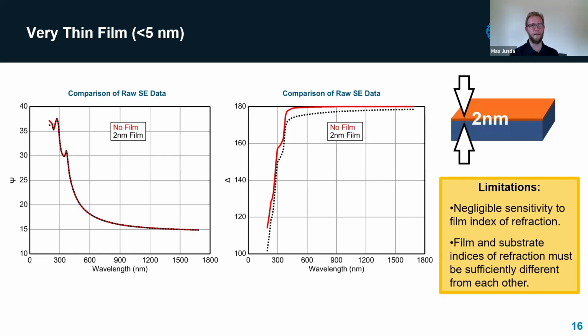And this gets to some of the limitations for very thin films. In particular, psi gives us a lot of sensitivity to what the properties of that film are, in particular, the index of refraction of the film. And since there is almost no change for psi between there being a film and there not being a film, what this means is we have very little sensitivity to what the index of refraction of the film itself is. So in cases of really thin films, we often have to just make educated assumptions on what the properties of that film are. And then the other thing is it requires that the index of refraction of the film and the index of refraction of the substrate have to be sufficiently different. If they're really close to each other, then this shift that we're seeing in delta, which is what's giving us the sensitivity to the thickness, will be minimized and we will have very poor or no sensitivity to thickness.